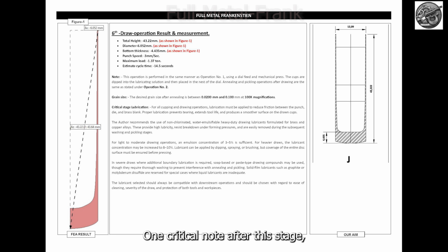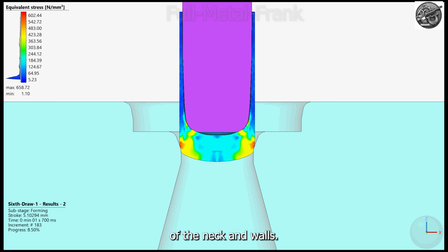One critical note. After this stage, only the base is annealed, not the entire case. This local annealing ensures the grain structure at the base is refined and soft enough for the upcoming head and primer pocket forming operations, while preserving the strength of the neck and walls.